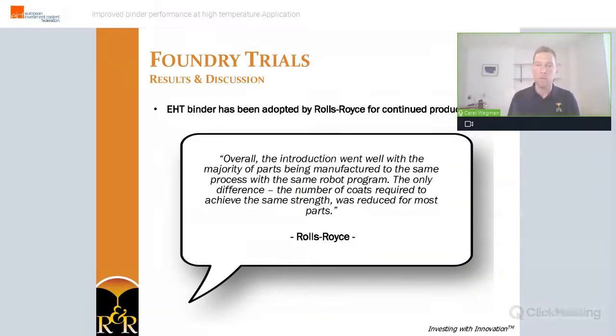Finally, the feedback from Rolls-Royce was very positive when EHT was introduced and it was adopted for continuous production of, for them, very important castings. Overall, the further introduction went very well, with the majority of the parts being manufactured to the same process with the same program, the only difference being that the number of coats required to achieve the same strength was reduced for most parts. So in the end, a technical paper was co-authored by Rolls-Royce, written by R&R, which is available through the EICF and by R&R directly.